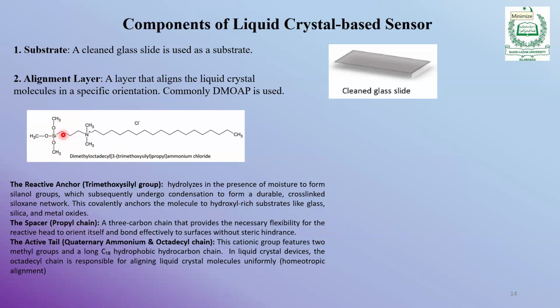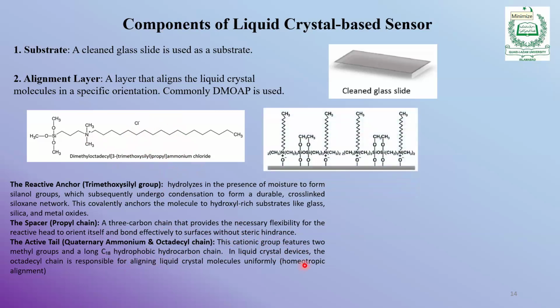The second is the propyl chain spacer. So this is separated by a 3-chain separator, which is necessary for the flexibility of the reactive head. So this is the reactive head, which will orient itself, and it will also align the crystal molecule. So it will bond effectively to surfaces without steric hindrance. The third part is the active tail, quaternary ammonium and octadecyl chain. This cationic group features two methyl groups and a long C18 hydrophobic hydrocarbon chain. In liquid crystal devices, the octadecyl chain is responsible for aligning the liquid crystal molecules uniformly. So this is after hydrolysis. On the glass substrate, this has been attached. So this is the DMOAP-coated slide.